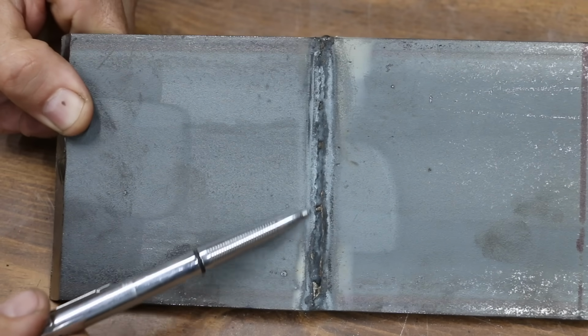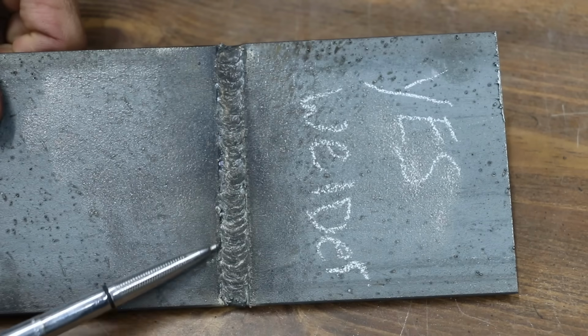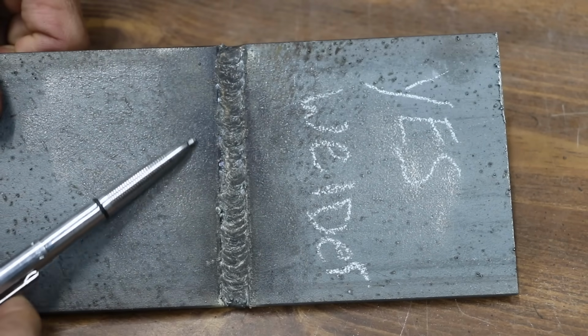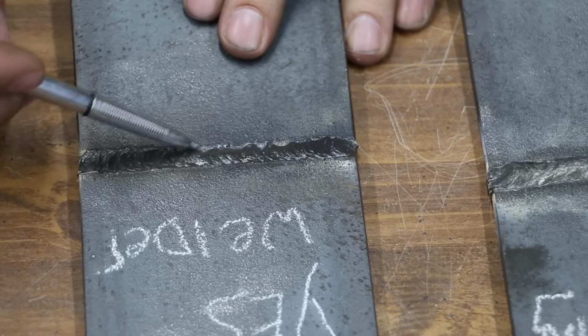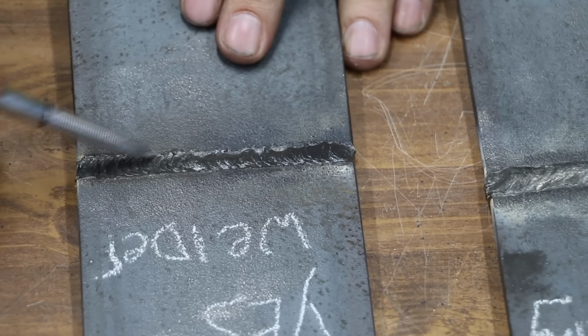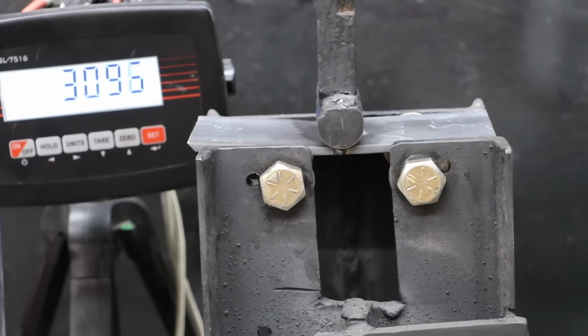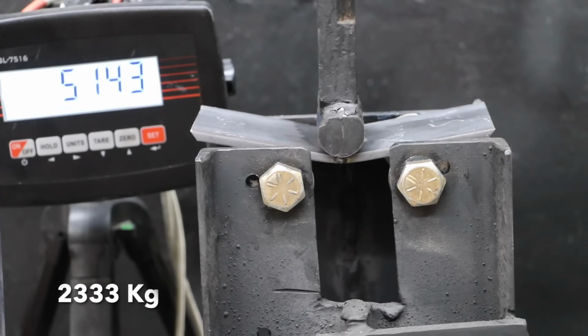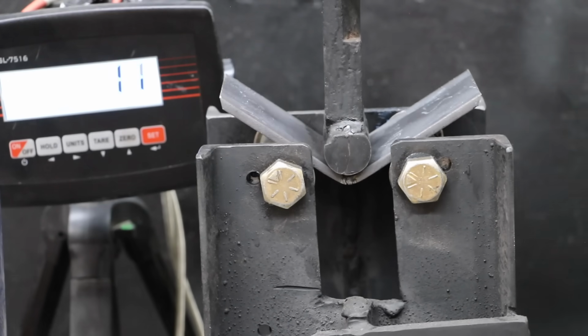We had a 3/32nd gap on all of these. As in for fill on both ends, did a good job tying into your edges. I would hit it with a grinder a little bit and put another cap pass right across the top of that. With the cap weld pass, the Yeswelder would have been even stronger, but 5,143 pounds is a very good performance.